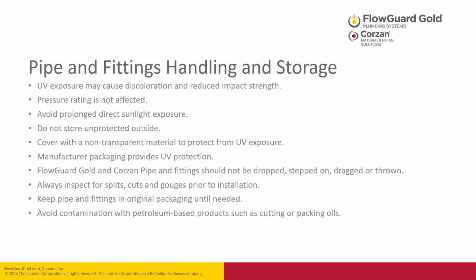When handling and storing FlowGuard Gold and Corzan, bear in mind that UV exposure may cause some discoloration and affect the impact strength of the products. The pressure rating is not affected, but it is important to avoid prolonged direct sunlight exposure in storage. Do not store it unprotected outside, and cover with a non-transparent material to protect from UV exposure. The manufacturer packaging should provide UV protection.